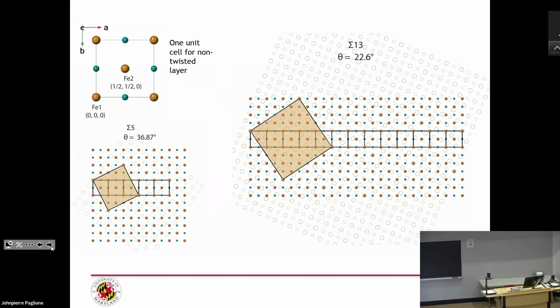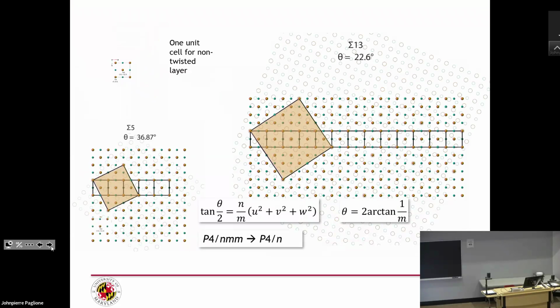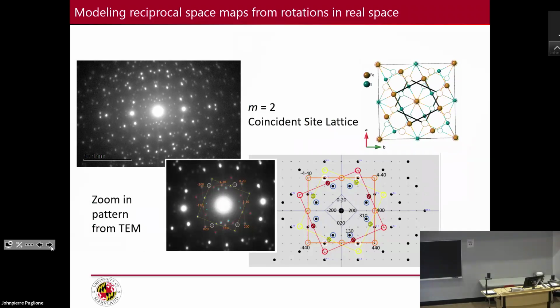And so we're able to solve some of these structures using something called coincident site superlattices, where crystallographically we're able to describe exactly how you can get a supercell like this from just twisting of your layers based on just the superlattice reflections. All right. You have to solve it in a new space group, but in any case, this is an example of a pattern that we were able to get with these solvothermal syntheses that at first looks very, very daunting, but my student Lahari was able to solve the structures and actually generate all the superlattice reflections with these coincident site superlattice models.